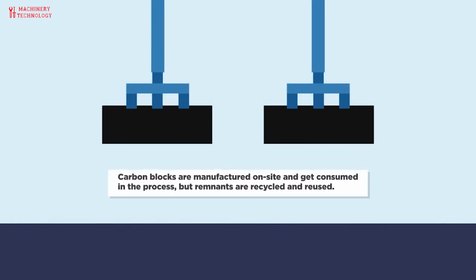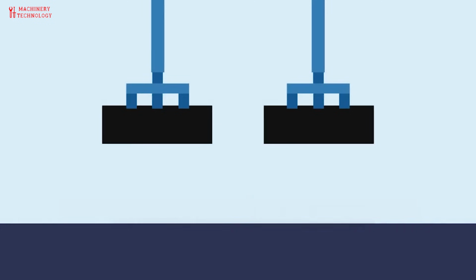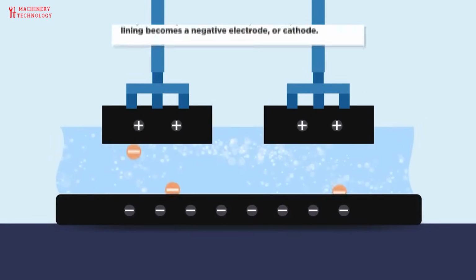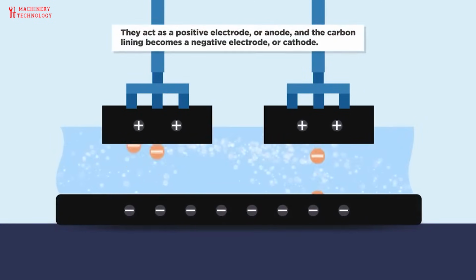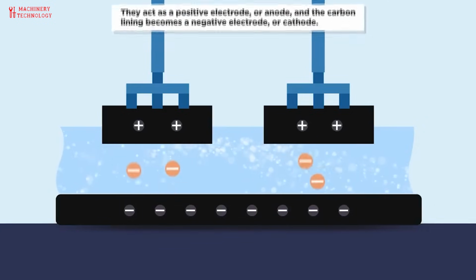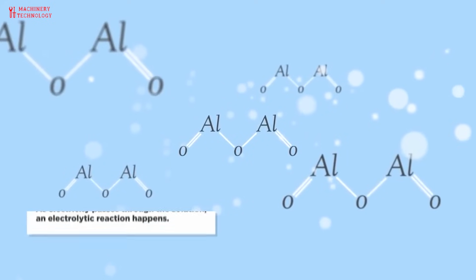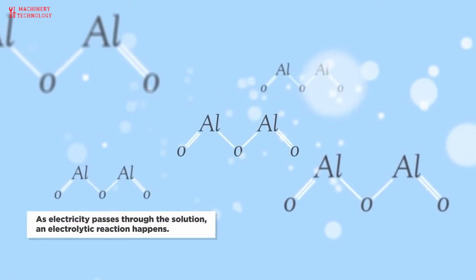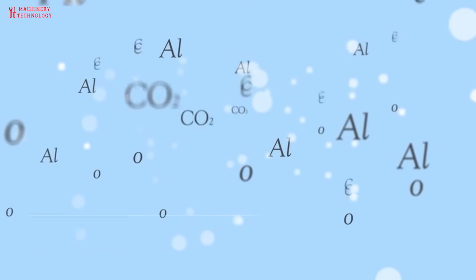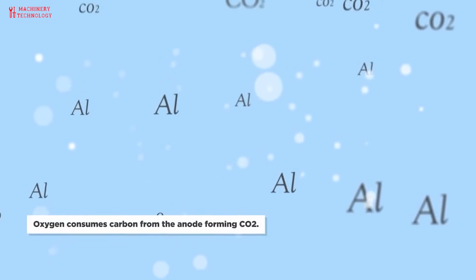Carbon blocks are manufactured on site and gradually consumed during operation, while remaining material is recycled and reused. The carbon blocks act as the positive electrode, or anode, while the carbon-lined cell becomes the negative electrode, or cathode. As electrical current passes through the molten electrolyte, an electrolytic reaction begins. The reaction separates alumina into molten aluminium and oxygen. Oxygen reacts with the carbon anode, forming carbon dioxide gas.